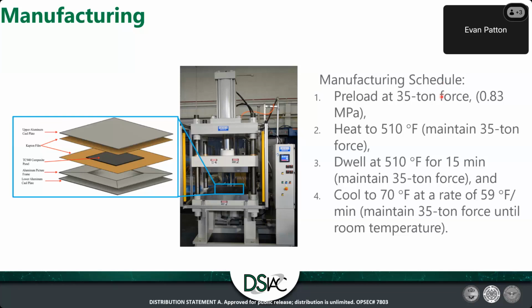And then at that point, at the 15-minute mark, it begins to cool. It's kind of hard to see in this picture, but there's a water-cooled chiller in the back. And that actually pipes conditioned water through these platens to cool them down at a relatively fast rate. We calculate it's around 59 degrees Fahrenheit per minute. That's driven by the capacity of the machine. So that's not by design or anything. It was just a characteristic of the setup that we had. So we just went with it because we weren't doing a crystallinity study on it.